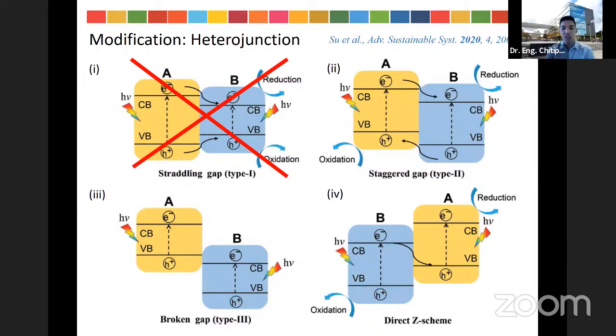And in type 3, the valence band top of material A is higher than the conduction band bottom of material B. So under light irradiation, electrons are excited in both materials, but no electron transfer happens even if they have some contact. So the recombination still happens in both materials.